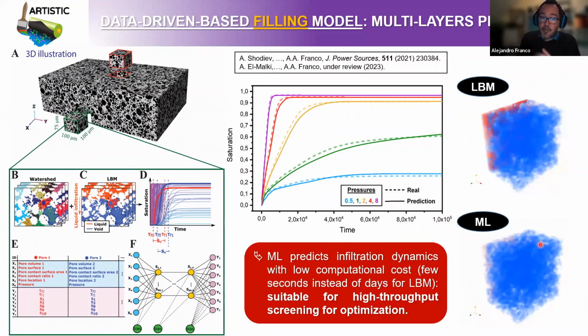This is why we have derived, by using machine learning, a surrogate version of this lattice-Boltzmann method, which has the advantage of being able to simulate the infiltration process of electrodes in 3D by the liquid electrolyte in a few seconds instead of a couple of days, okay? And here, what we use as a training data set is the results arising from the lattice-Boltzmann method. And we have actually defined different descriptors. For instance, the final saturation of each of the pores in a given microstructure, the time that the pore takes to be fully filled or partially filled, and so on and so forth.